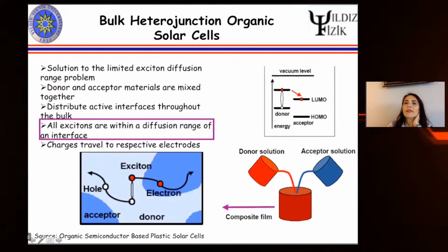Instead of coating each individual layer on top of each other, they mix up this donor and the acceptor in the same solvent, and they make a kind of composite film. The idea was to distribute the heterojunction to the bulk of the film. Therefore, it's called the bulk heterojunction organic solar cell.